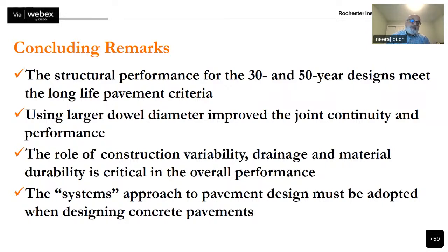That's one reason. The joints are much tighter. The width of the joint is much tighter. So you are engaging a fair amount of aggregate interlock that allows for load transfer efficiency. And the biggest advantage, especially for ultra thin white topping, is that it is sitting on an asphalt pavement, which provides a significant amount of support under the concrete slab. So those are the reasons why in an ultra thin white topping or a thin white topping, we do not provide dowel bars, because the necessity is not there.